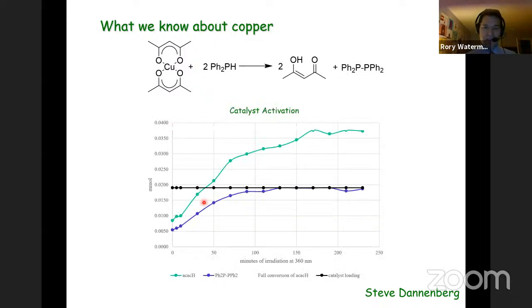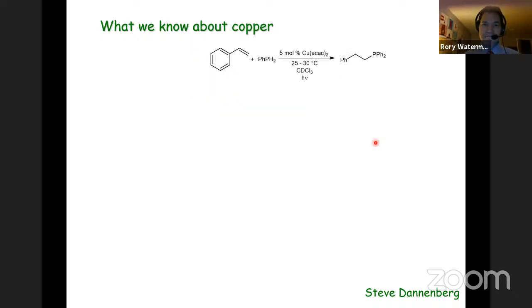And what I can do is illustrate for you here the formation of the diphosphine, the tetraphenyldiphosphine. This black line is the theoretical maximum. So we peg ourselves exactly to making the one equivalent. And we also then track rapidly with making 2 equivalents of ACAC. So really what we're thinking is that the copper 2 is being sharply converted right into copper 1, and it's copper 1 that's doing the work. That's not a surprising observation with how a lot of copper catalysts work, but it's very clean in the way in which phosphorus can support that redox chemistry.